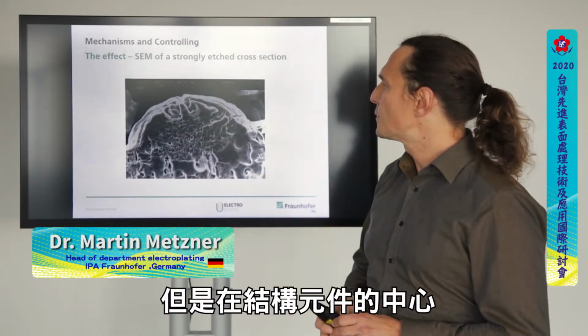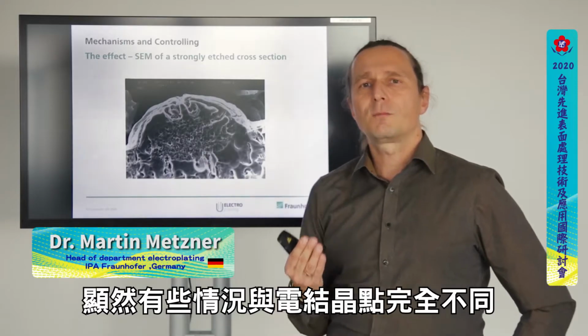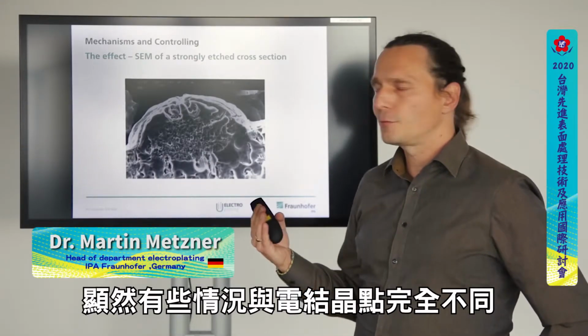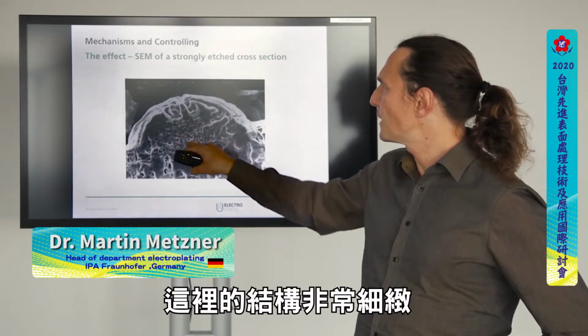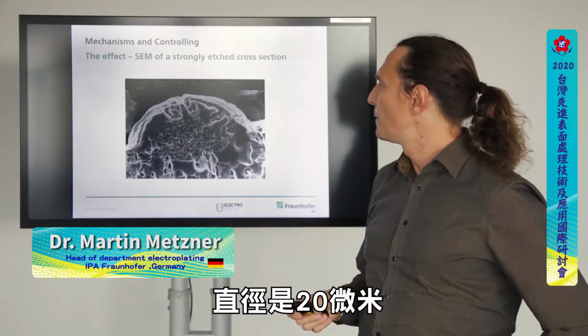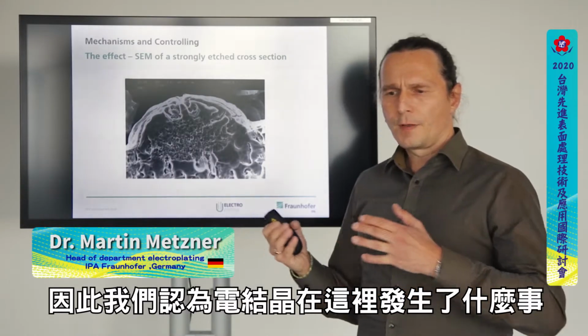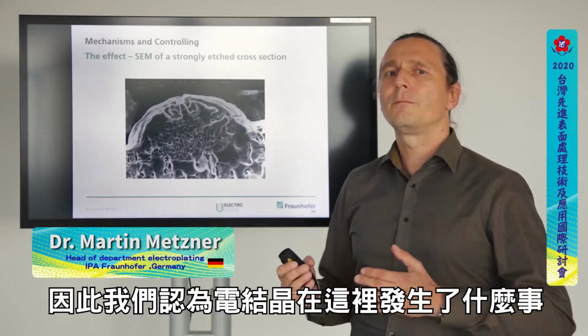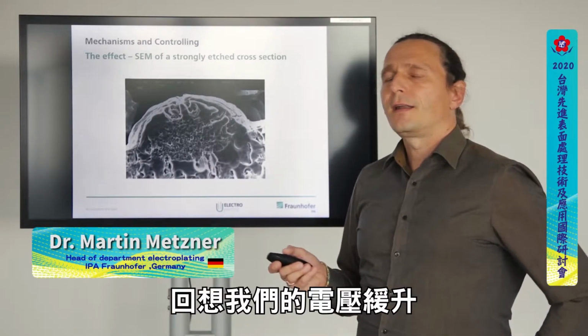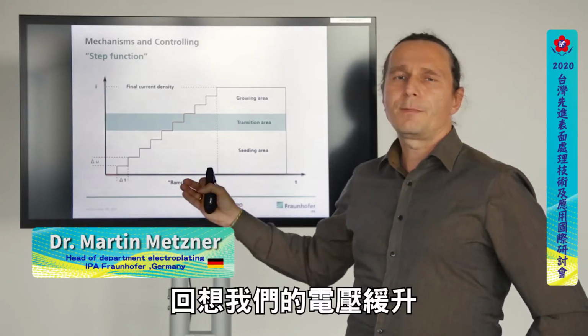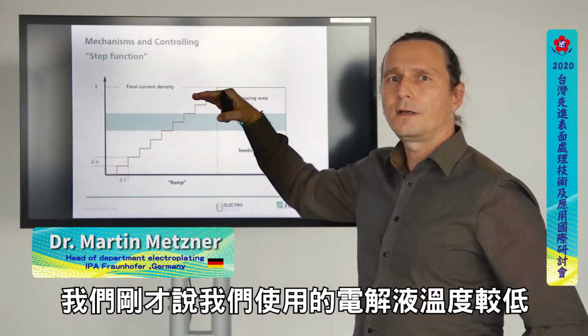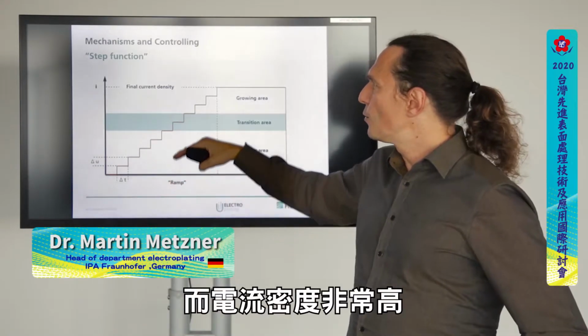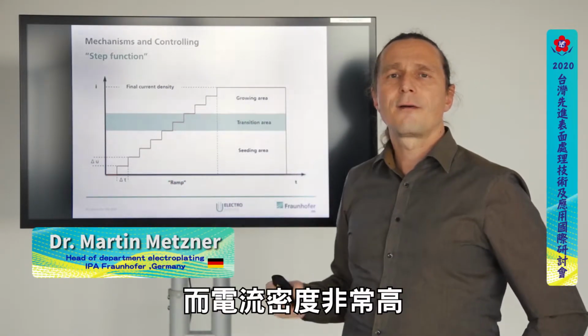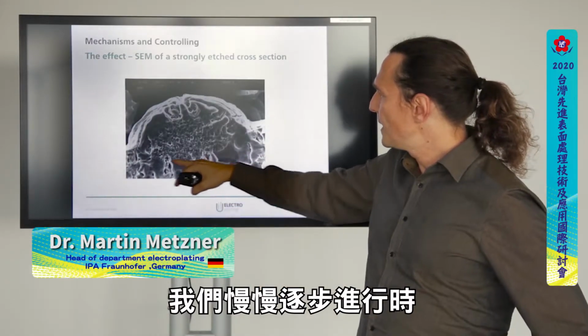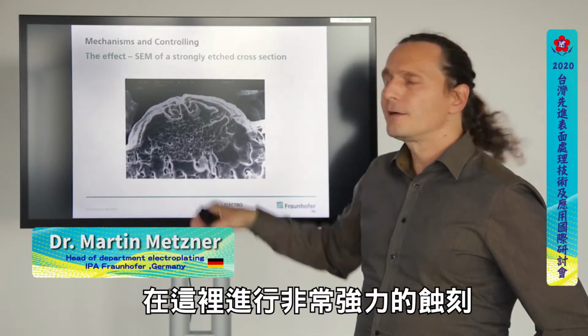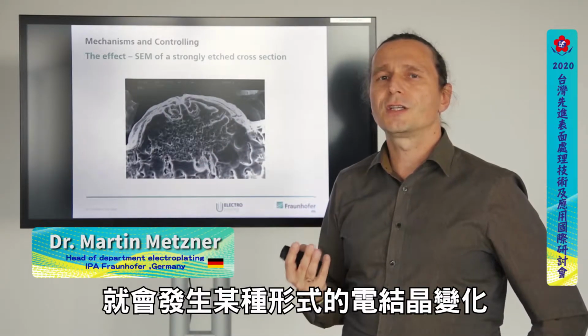But in the center of our structure element, there's obviously something completely different from the point of electrocrystallization. We see a very, very fine structure here. Again, you see here the size, 20 microns of diameter. So we thought, okay, something happens in here with the electrocrystallization. And when we think back, what we do in our ramp is that, as I told you before, we use a relatively low electrolyte temperature and we go up to very, very high current densities. And obviously, when we do this step by step, then with a very sharp edge in there, something happens with a kind of change in electrocrystallization.